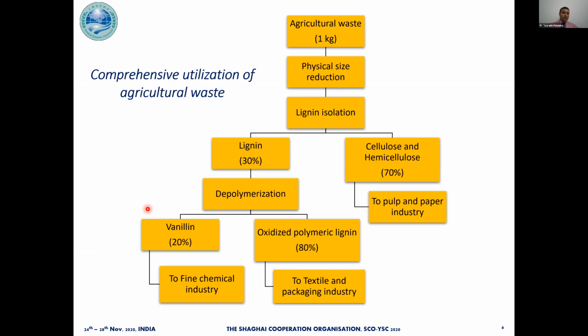Now, I'm currently working with a startup company on producing virgin cellulose pulp fibers, vanillin and oxidized polymeric lignin from agricultural waste. The biomass is first fractionated into cellulose, hemicellulose, and lignin fractions by using a benign organosolv process, followed by the oxidative depolymerization of lignin to yield vanillin. Now, vanillin is a platform molecule owing to the multiple functional groups on it, and apart from its utility as a flavoring agent that fetches good revenue.